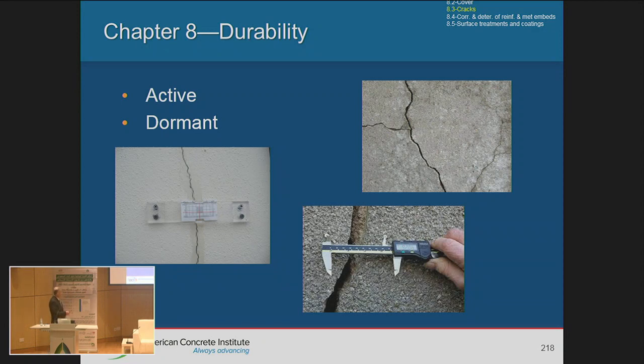As mentioned, we need to look if it's active or dormant. One thing is, for example, to measure the width of the crack over periods of time, or put a device on it and see how the crack is moving. Active cracks mean we need to take some actions. They need to be addressed and corrected. Dormant cracks mean that the crack is not moving. There's no deterioration or movement in the structure, but a dormant crack could become an active crack in the future.